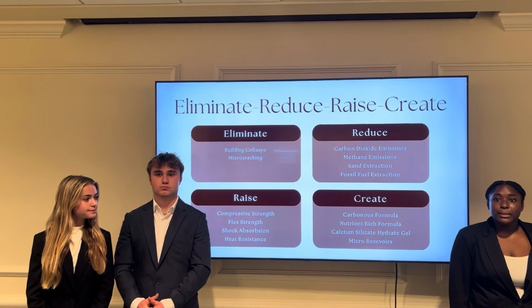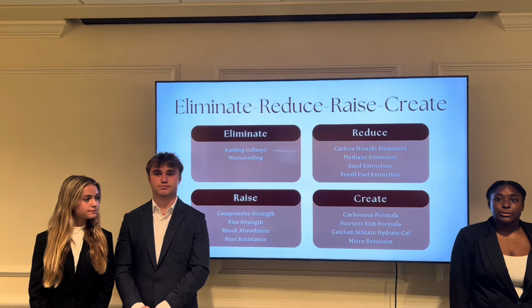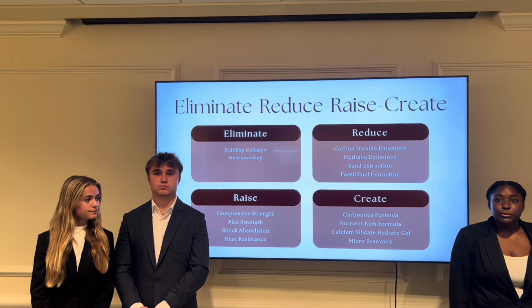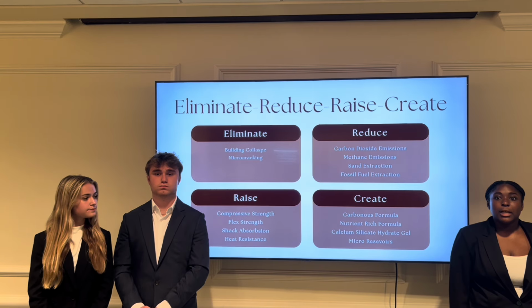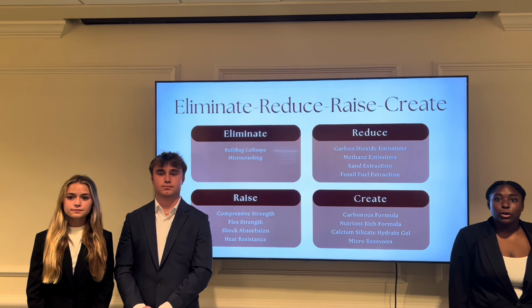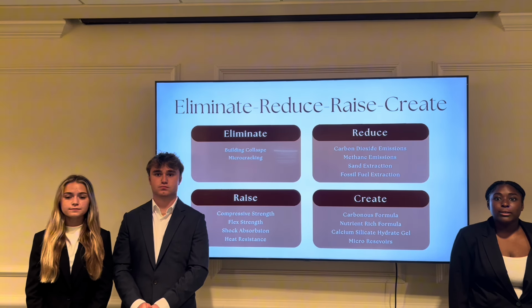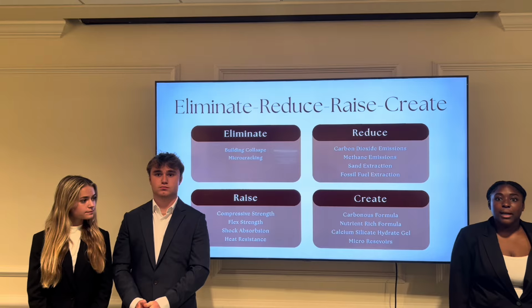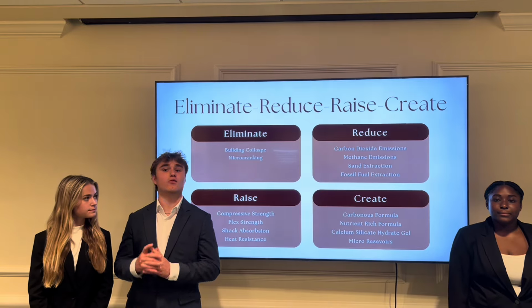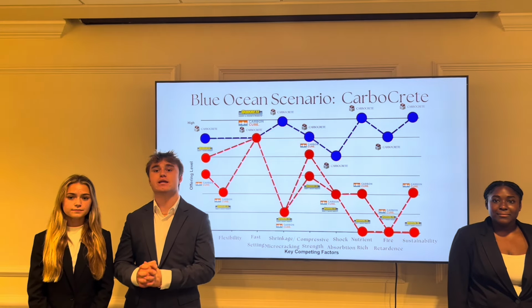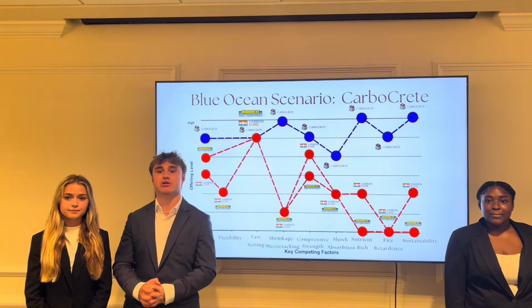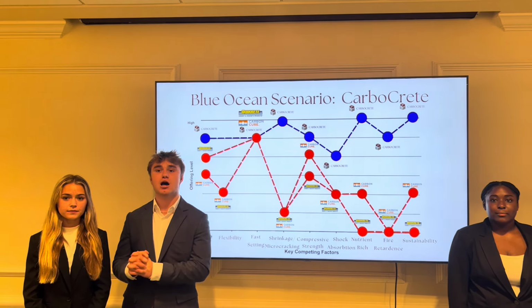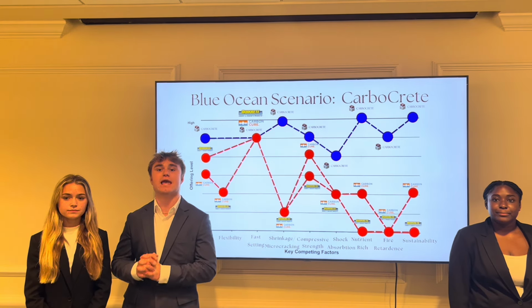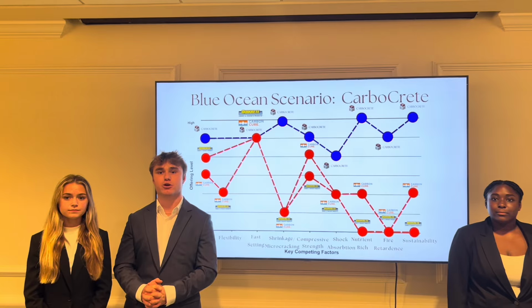We reduce CO2 emissions, methane emissions, and sand extraction. We raise compressive and flexural strength, shock absorption, and heat resistance. We create a carbon-rich, nutrient-enhanced concrete matrix, forming stronger calcium silicate hydrate gel with built-in micro-reservoirs for durability. CarboCrete is the only solution that combines high strength, flexibility, shock absorption, reduced shrinkage, and average setting times with measurable environmental impact. Additionally, we reduce methane, fossil fuel use, and sand extraction, all while being fire retardant.